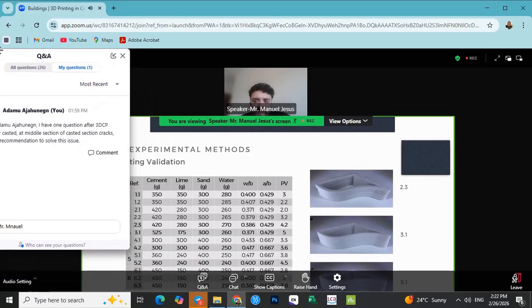This value is largely driven by the particle size of these materials. Finer particles like cement have a higher surface area and therefore require more water to stay workable for printing. On the right, we have some pictures of the best prototype that we printed.